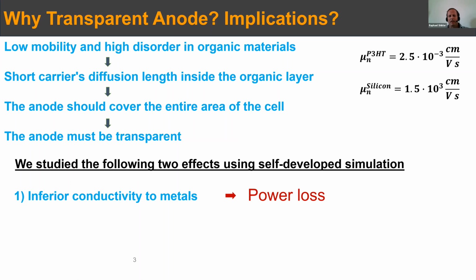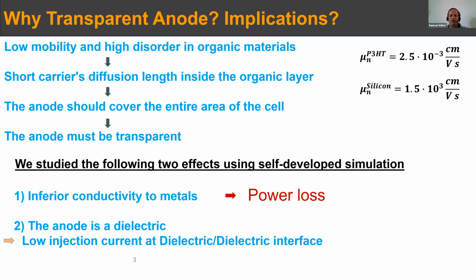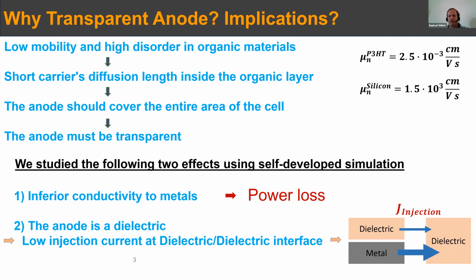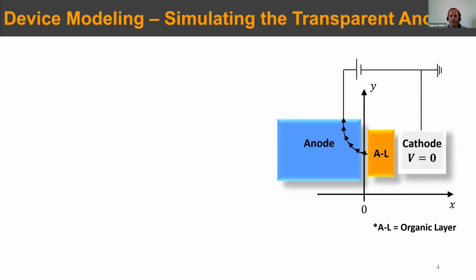But we managed to develop a simulation methodology that can help predict, from the point of view of planning, what is expected. The other thing is that the anode not only has poor conductivity, it is a dielectric, and as such it has different permittivity than metal, and this will lead to low injection current at the dielectric interface. So a metal, compared to a metal-dielectric interface, has a much higher injection current than a dielectric. I will cover both of these.